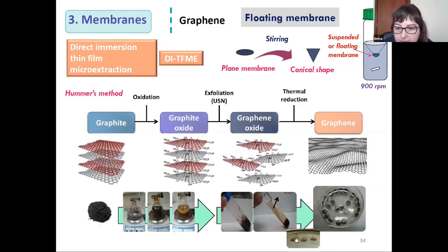As we can see here, this is how to prepare the membranes. We have this graphene oxide here, and we deposited it onto glass substrates of this size, and then we have to dry it at around 80 degrees for 8-10 minutes, and then we have these black membranes. We take this and put it into a glass containing water, because these membranes have the property of floatability in water, and we store them in this way before analysis.